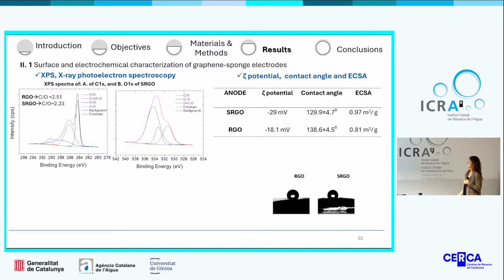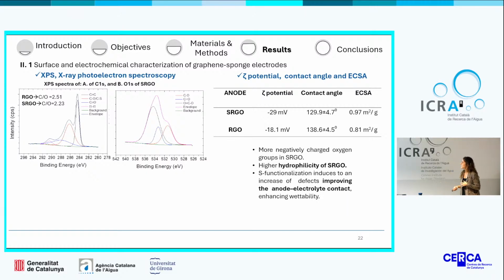On the other hand, the zeta potential, contact angle, and the electrochemically active surface area were also measured. According to this result, a more negative zeta potential was observed in the SRGO electrode, which is again probably a consequence of the appearance of different sulfur oxide containing groups. Also, a decrease of the contact angle was observed, which means that our material is more hydrophilic, and also a slight increase in comparison with RGO in the electrochemically active surface area, which is probably a consequence of the different S-functionalized groups, which improve the anode-electrolyte contact, enhancing the wettability as well.